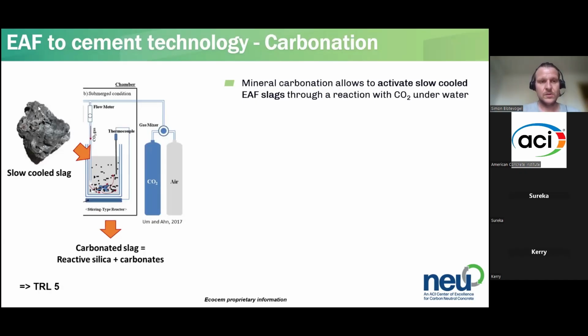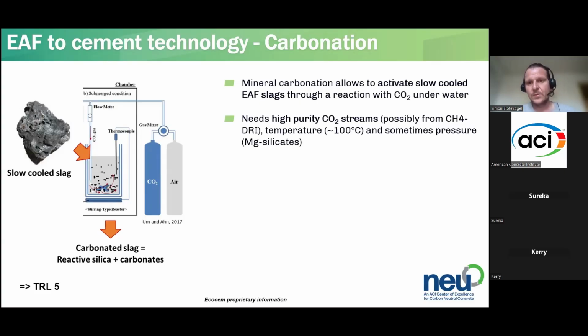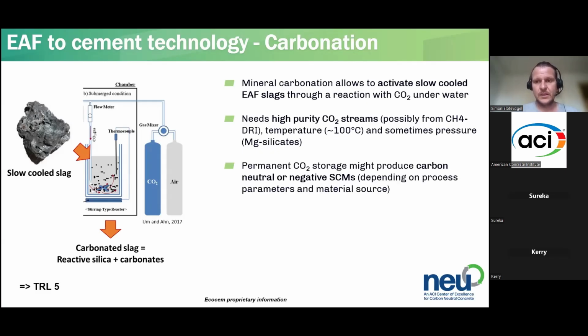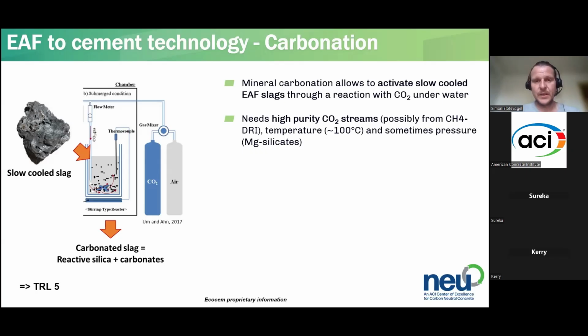You've certainly heard of this. So you would take your slow cool slag that is non-reactive, put it in some sort of reactor, add gas, maybe temperature, maybe pressure, and then yield reactive silica and carbonates. This would need high purity CO2 streams, especially when you want to carbonate magnesium-bearing silicates that need a bit of temperature and pressure. And you don't want to put pressure on a gas that contains only minor amounts of CO2 because you would lose all the energy put on the other gases. They might come from methane run DRI plants that have quite high purity CO2 streams. So for EAF slags, there's a certain logic to use this.